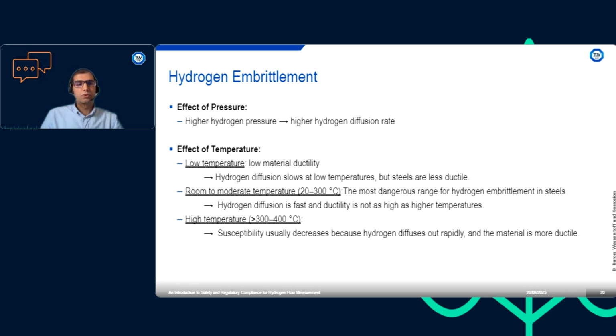At room temperature to moderate temperature, such as 300 degrees Celsius, that's the most dangerous range, basically, because hydrogen can diffuse very well at that temperature, and the ductility of the material is not as high as at higher temperatures. So that's the most dangerous zone for hydrogen embrittlement. And then at high temperatures, because the ductility of the material is higher, there is a lower risk. And also the hydrogen that diffuses into the structure of the material can escape easily.